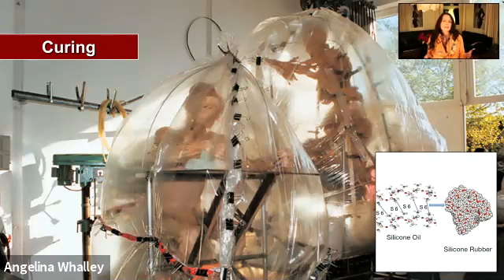Because Gunther figured out, or let me tell you, that normally you stir the silicone bath with the hardener together, and then you have a pot life. Pot life means the time you have for impregnation is very much limited. Before Gunther had this idea of gas curing, it was only possible to have pretty small specimens, and only the separation of the curing process and the impregnation process allowed us to do large specimens, full body specimens, or even animals of the size of a giraffe.